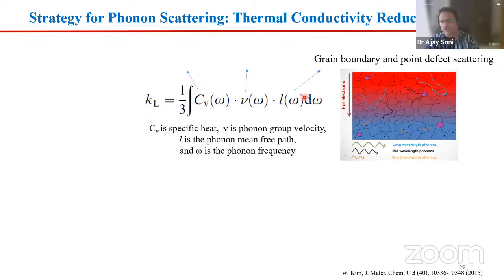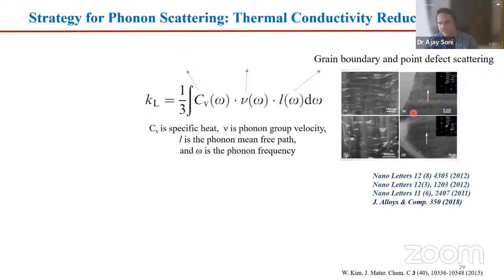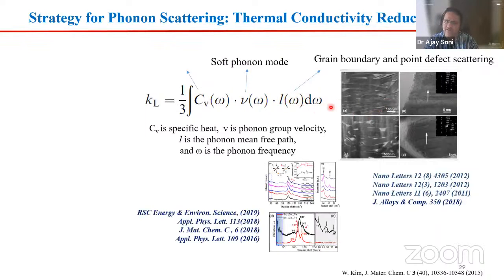So, okay. When you create nanostructures, you are creating a lot of defects like the interfaces and the grain boundaries in the materials that can become the phonon scattering centers, which can reduce the thermal conductivity. Okay, so this we have done in telluride-based materials, where we grew these materials in nanoform and then made a composite out of it, and we could achieve a good thermoelectric figure of merit by controlling the mean free path of the phonons.